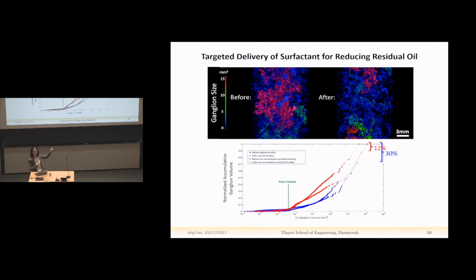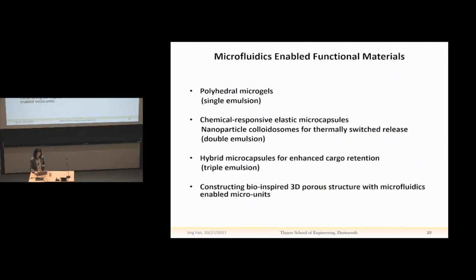Although I want to point out that we shouldn't interpret these numbers quantitatively, we did repeat this experiment a couple times, and qualitatively this confirmed our hypothesis that by using these smart capsules, we can save the amount of surfactant in order to get the same oil recovery effect. Or by using the same amount of surfactant, we can get better oil recovery efficacy by using the capsules. Okay. So this is the second project I want to introduce.